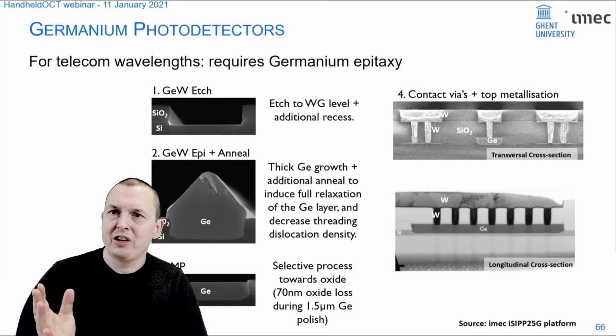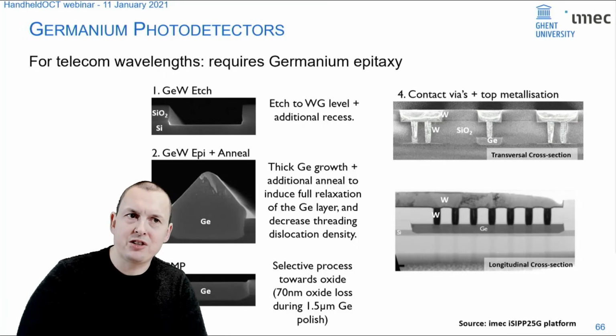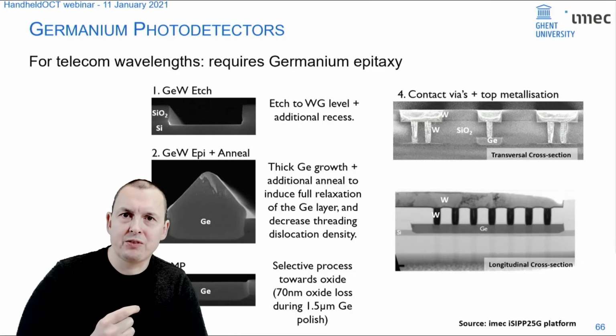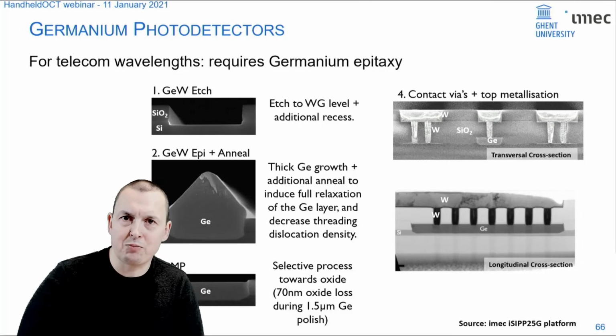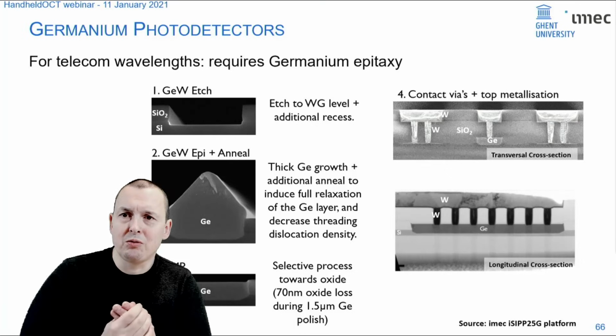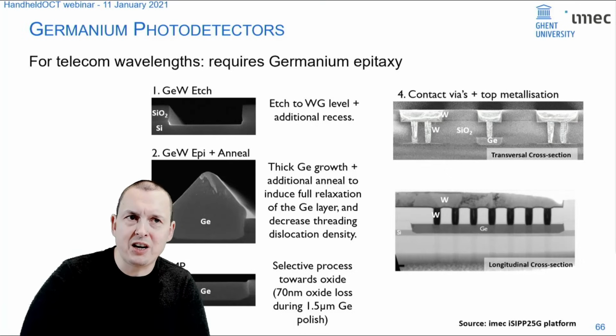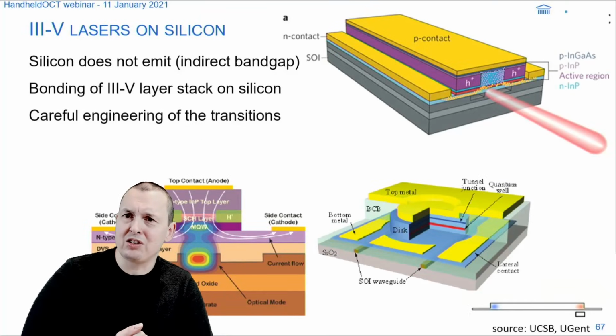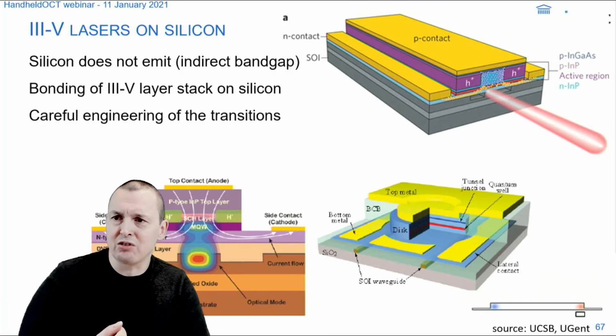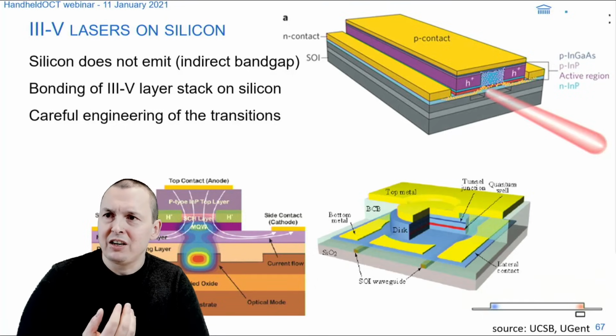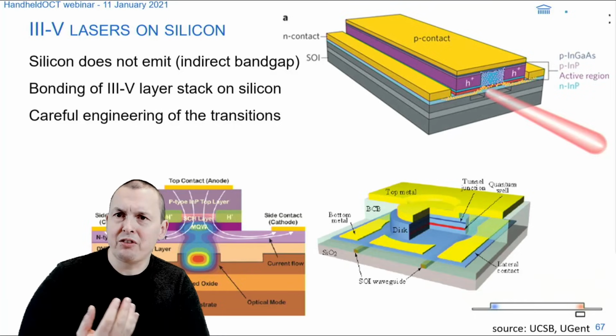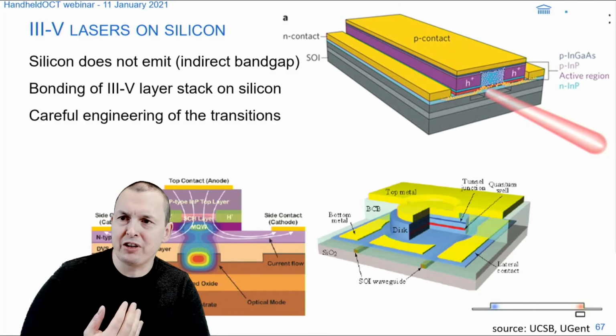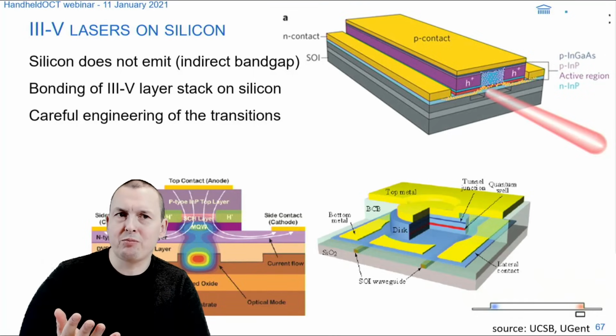Now that's photo detection. The biggest challenge in silicon photonics is its lack of a light source. And there's no really good trick to pull in a CMOS fab to make silicon emit light, especially at telecom wavelengths. So in the end, the approach is now to try and bring III-V materials to your silicon to make a laser. And the first approach that's still quite popular, and that's also part of commercial products, for instance at Intel, is to basically just glue or bond III-V layers on top of your silicon photonics and then process a laser in it. That works quite well, but it's a quite convoluted process.